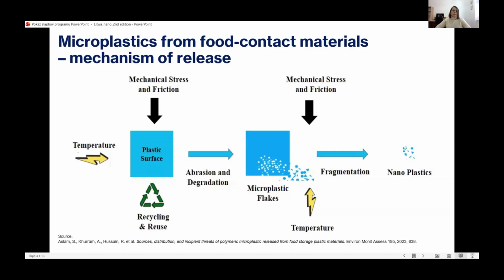Packaging materials, particularly polymers with lower structural stability, can undergo degradation when exposed to relevant temperatures, light, or fatty food matrices. These kinds of stressors accelerate physical and chemical breakdown of the material, leading to the release of microplastics and, as a consequence, the migration of associated chemical additives such as plasticizers. Studies show that the rate of microplastic release increases significantly under heat, such as during microwaving or prolonged storage at elevated temperatures. Likewise, foods with a high lipid content promote the extraction of additives because many plasticizers and polymer-related compounds are highly lipophilic.